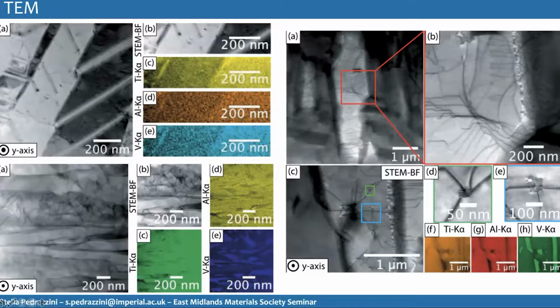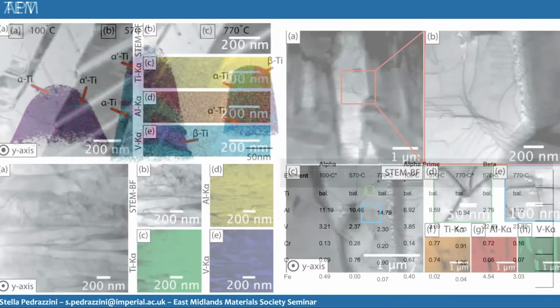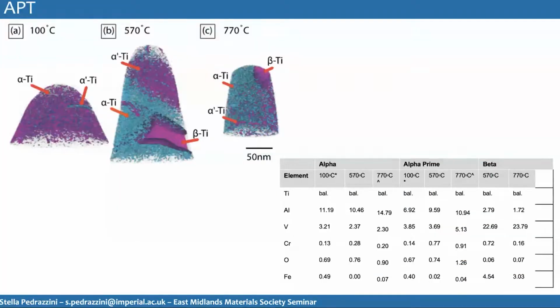So in this case, looking at the 3 different samples, we can already tell that there's a huge difference between them. Now, the next thing to do was to look at oxygen content. I think all the titanium metallurgists out there are probably cringing looking at this line, the oxygen content, and thinking that this is enough to explain the brittleness. It probably is, but the only brittle sample here was the 770.